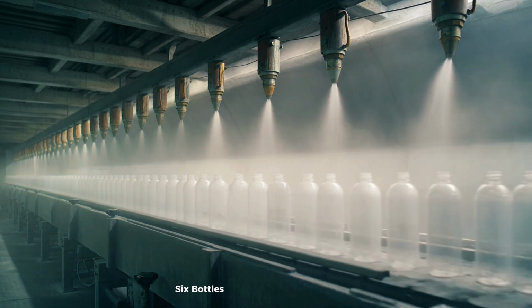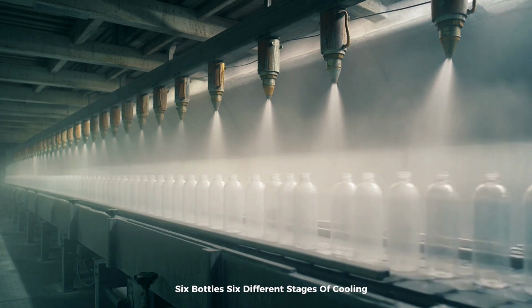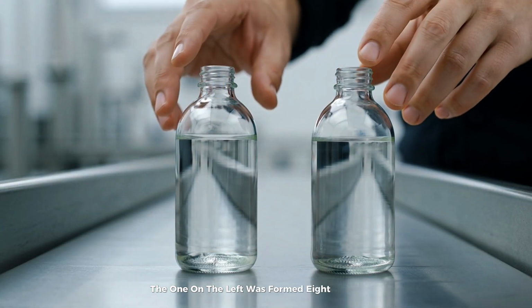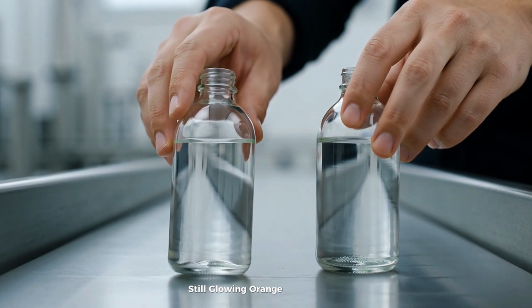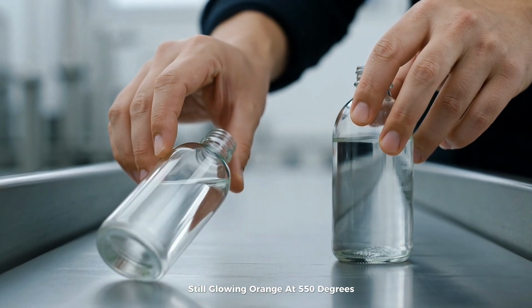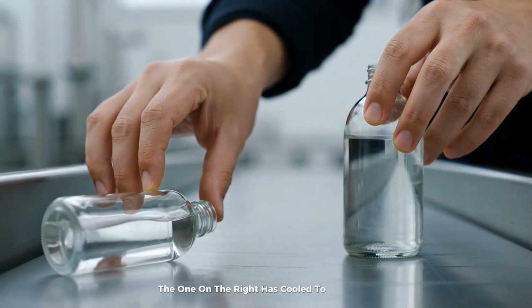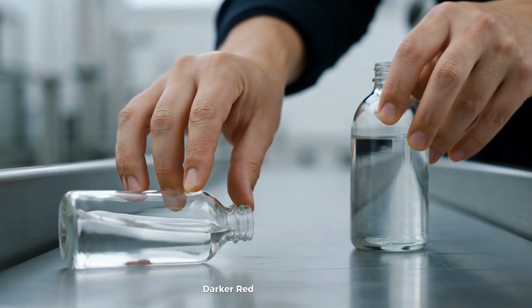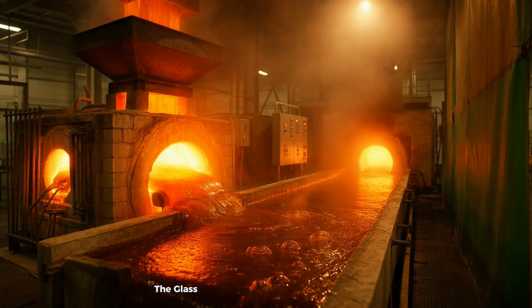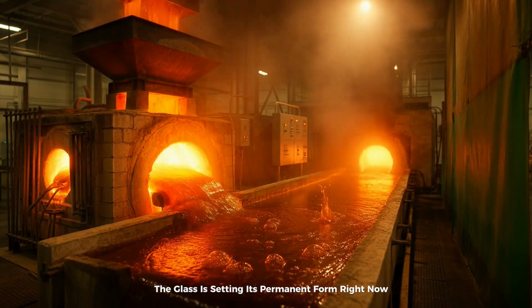6 bottles. 6 different stages of cooling. The one on the left was formed 8 seconds ago, still glowing orange at 550 degrees. The one on the right has cooled to 400 degrees, darker red, the shape locked. The glass is setting its permanent form right now.